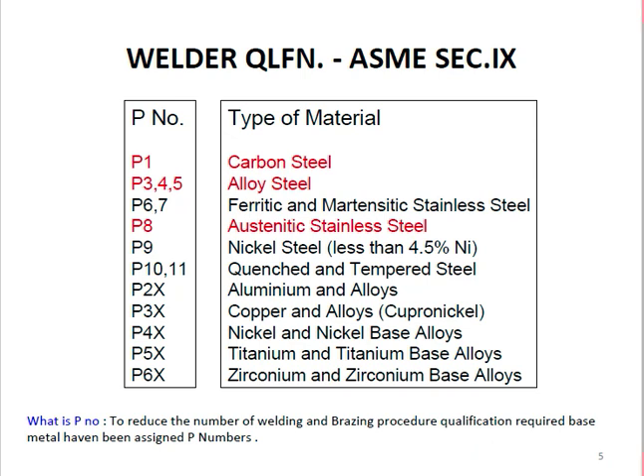The P-number is very important. To reduce the number of welding and brazing procedure qualifications required, base metals have been assigned P-numbers. P1 is carbon steel; P3, P4 are alloy steels; P6, P7 are ferritic/martensitic stainless steel; P8 is austenitic stainless steel. We need to know the P-number of the material before performing welder qualification.